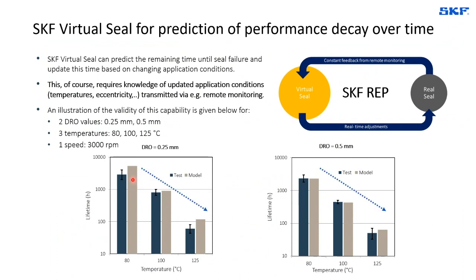What is also interesting is that we see the decrease over the temperature range of this life expectancy, or lifetime, in number of hours. As we increase the temperature, lifetime is dropping. This means that if we are able, like I was showing earlier, to predict the effect of the temperature changing in application, we can then update the time remaining until seal failure.